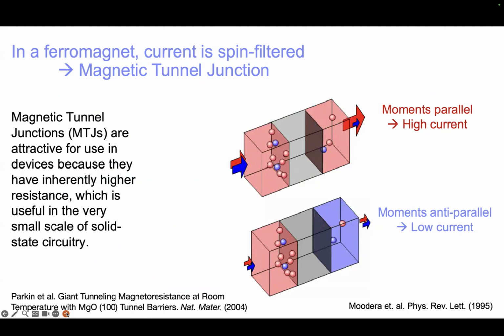And now it turns out, just as in a metallic spin valve, this device, which is based on quantum mechanical tunneling of electrons from one magnetic electrode to the other through this insulating layer, leads to even larger changes in the conductance of this sandwich structure. The physics, though, is entirely different. It's no longer spin-dependent scattering. It's now spin-dependent conductance or tunneling through the gray barrier.